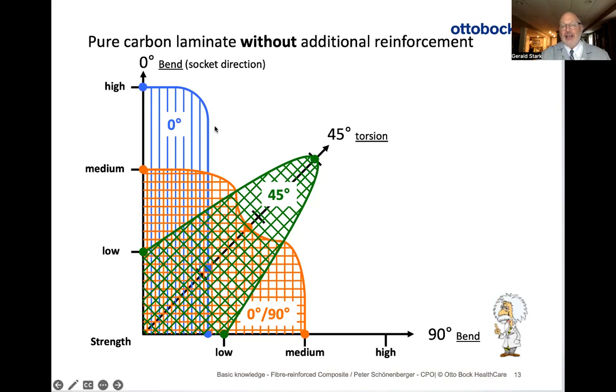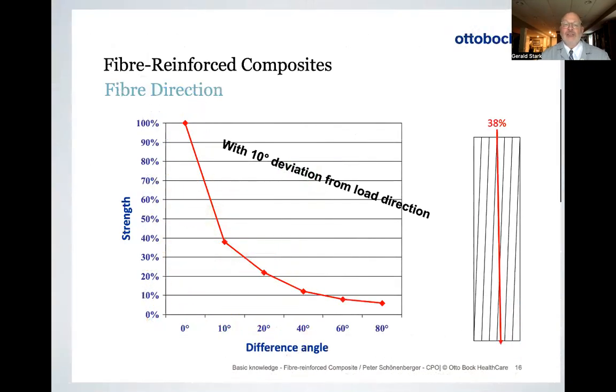In orthotics, we have to do multiple things because there's multiple torsions, multiple levels. So they typically add 5 different layers to accommodate for those different movements. The reason we worry so much about this weave and the angle of the fiber is that if we have just 10% deviation from the load direction, we decrease the load strength by 38%. So if we're off just a little bit, it makes a big difference.